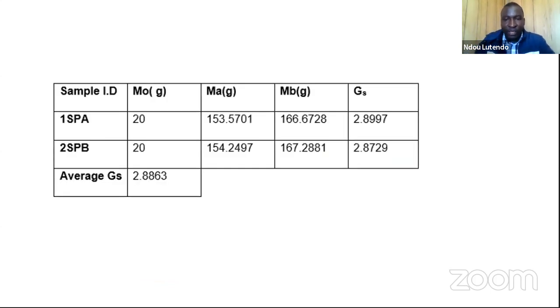So my specific gravity was 2.8. And the benchmark for strength, geotechnically, when you are characterizing, is that if you have a specific gravity of over 1.5, your material is very strong. And obviously it should be strong if we have quartz. Quartz is one of the minerals that are resistant to weathering, which proves that they are strong.